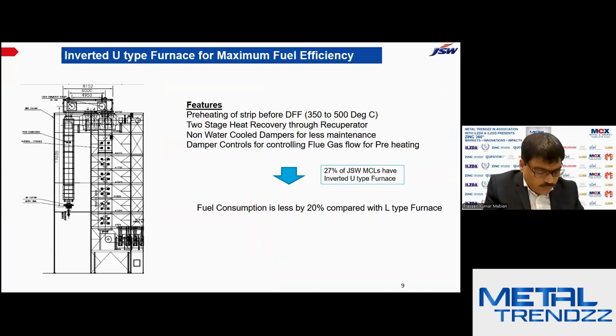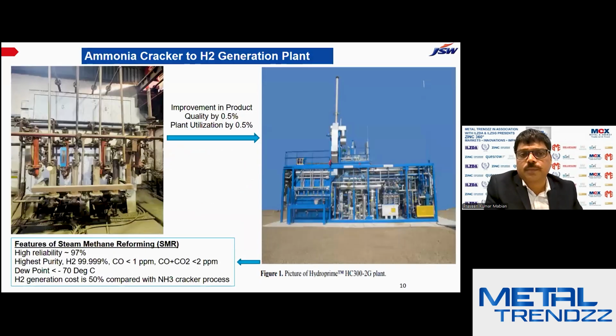This is not a new thing. The inverted U-type furnace increases the efficiency of the furnace, the fuel efficiency. 27% of the JSW metal coating lines have an inverted U-type furnace. Around 20% less fuel is consumed compared to the conventional horizontal furnace or L-type furnace.